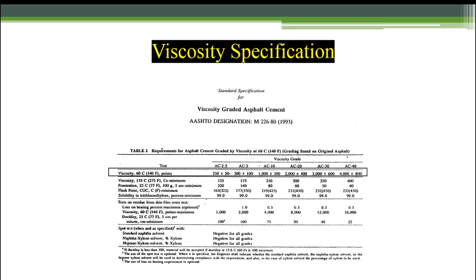And asphalt, again, what we're dealing with essentially on one side is we don't want it to rut, we want it to be durable. Well, if it's going to rut, typically it's going to rut because the asphalt's soft. So we're kind of getting a test, a specification that we can use to control a little bit of the stability side of the asphalt, A in the 3 A's of our asphalt mix. So as we look across, you can see there were 6 grades in the viscosity graded AC, from AC 2.5 up to AC 40. As you go up the line, essentially that's a set point with a tolerance on viscosity measured in Poises. And so as we're going left to right now on the viscosity chart, the material's getting stiffer, right? Higher viscosity number, stiffer material.